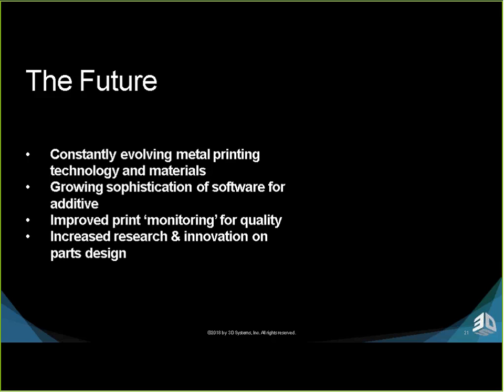Combine that with the fact that now we're able to push closer to the envelope of ideal, a lot closer to the mechanical properties actually required to meet an application. What that's going to require is better print monitoring. And so you'll see companies working a lot more aggressively. There's a little bit out there now. A lot of this is traditionally called melt pool monitoring. What it really is, is kind of thermal weld pool monitoring.